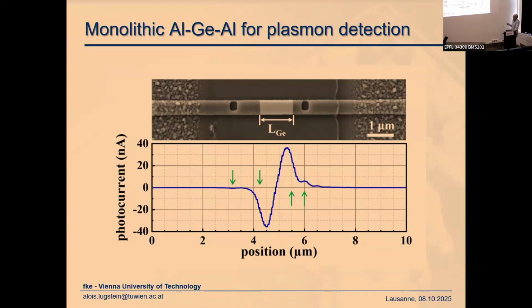And when we do a scanning along this line, you see that we get a very small peak here, a larger peak here, then one in the opposite direction, and once again here when we are at the top of this hole. So this shows that again, this coupler works not as good as this focus grating coupler, but still we got some small signal. Anyway, this one is larger than this one. The reason therefore is that the propagation length is much shorter here than here.